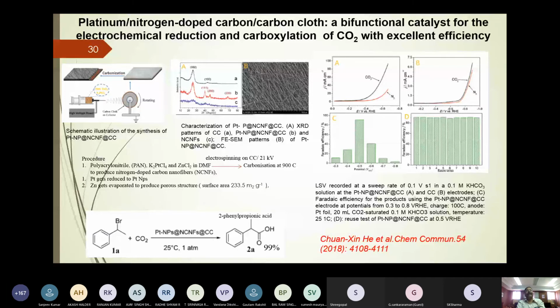There they obtain the carbonization at 900 centigrade, where the platinum gets reduced to nanoparticles and zinc gets evaporated to produce porous structures. As usual, SEM shows the morphological characteristics of platinum nanoparticles doped on carbon cloth. XRD shows the presence, and then voltammetry shows higher current plus higher onset potential for the conversion of CO2. There we can see from the SEM, and then the top is the CV, and the bottom is the Faradaic efficiency for the conversion of these organic bromides into 2-phenylpropionic acid with a yield of 99%.